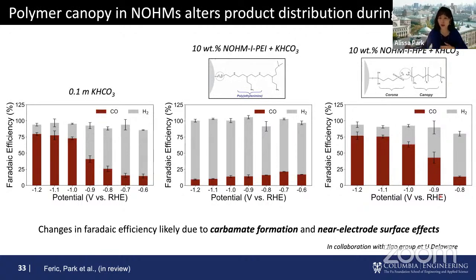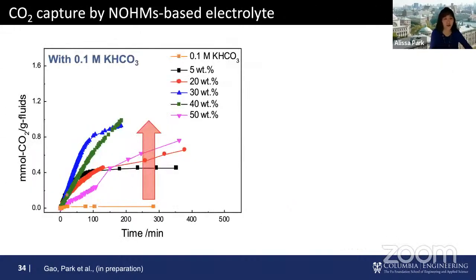But we had a lot higher per pass conversion of CO2 because we are loading a lot more CO2 into the electrolyte. The reason this conversion is lower and the Faraday efficiency is different is that the carbamate is not electrochemically active. I don't have data here, but by increasing the reaction temperature, you release the carbamate back into CO2, which is electrochemically active, so you can convert back to much more CO2 conversion to CO at higher temperatures.